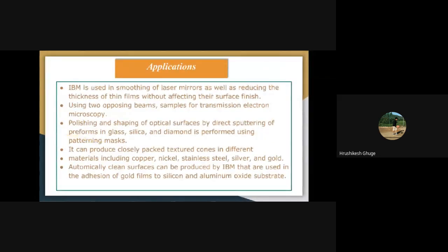Then let us discuss the last part, that is applications. This IBM is used in smoothing of laser mirrors, as well as reducing the thickness of thin film without affecting their surface finish. In this regard, thinning of silicon samples to a thickness of 10 to 15 micron has been reported by one researcher using argon ions impinging at normal incidence. Then using two opposing beams, a thin circular region on a rotating sample can produce a sample for a transmission electron microscope. Another application is polishing and shaping of optical surfaces by direct sputtering of preforms in glass, silica, and diamond, prepared using a patterning mask.